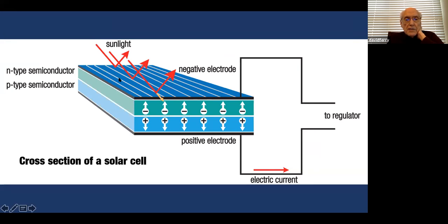Now these white lines up here are contacts because you have to have a contact to get the current out. And that's kind of a good days, bad days, half full glass type of thing, because the contact has to be large enough to carry the current without too much resistance. But if it covers the whole surface, the light doesn't get in because the metal reflects the light back. So that's where the trade-off has to come. And in addition, the silicon surface will also reflect some of the light. So you use anti-reflection coatings there, just like on your glasses, to help the light get in. Okay, that's a normal PN junction.